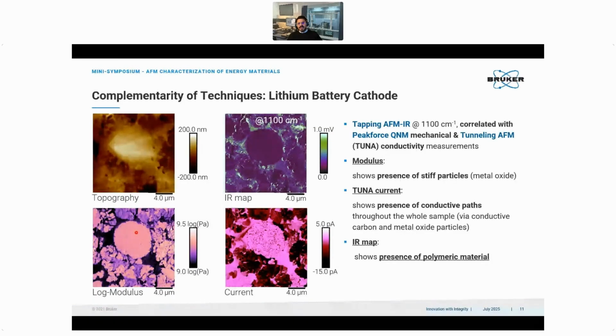stiffer than other grains. And then we can look also into the current in PeakForce TUNA or in TUNA measurements, like the ones that we have seen in the presentations before. We can see where areas are more conductive than others. And then we actually add into that the chemistry. So here we can identify the presence of some polymeric materials in there.